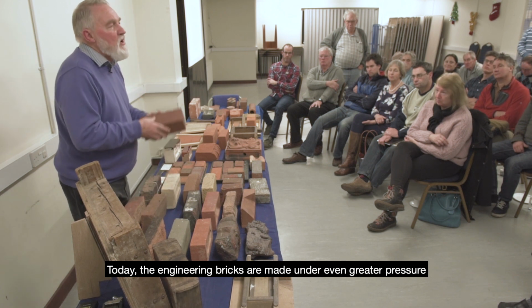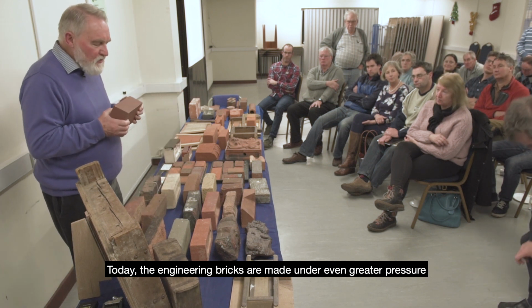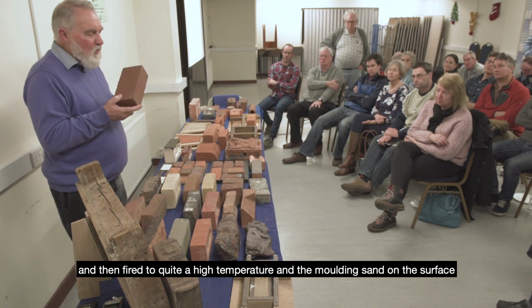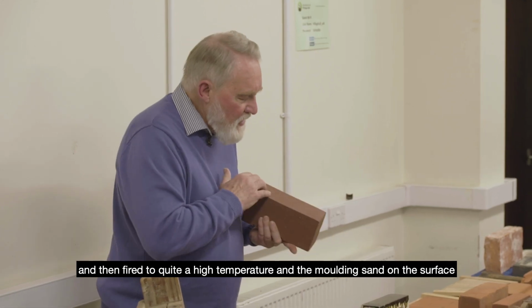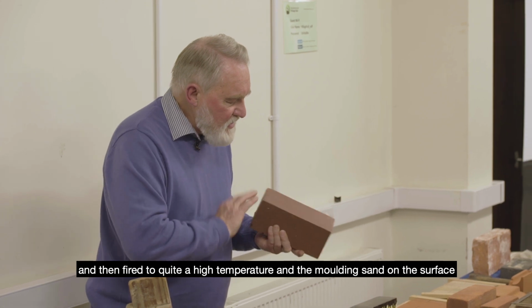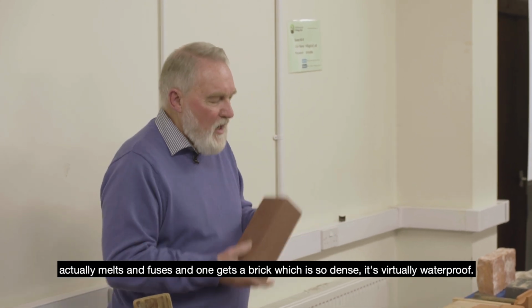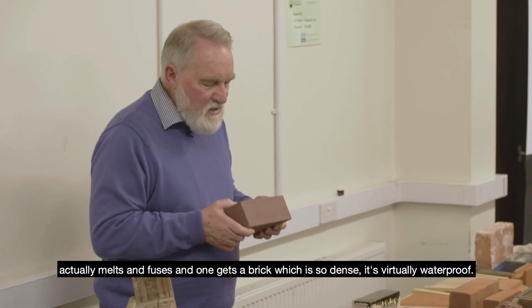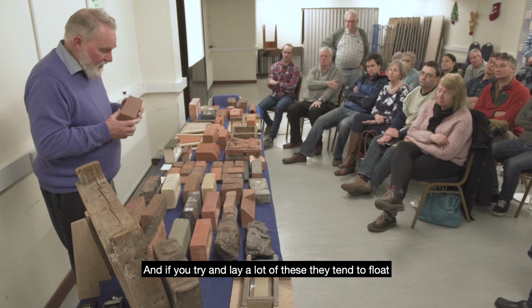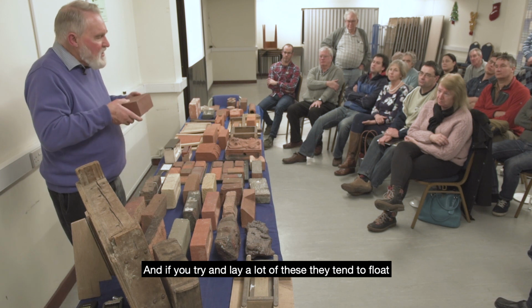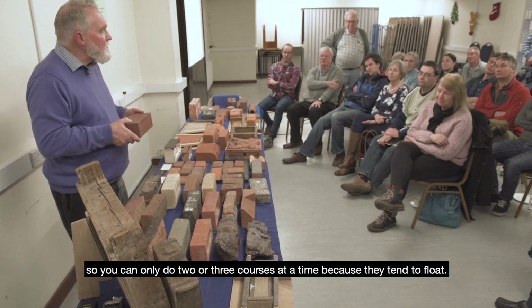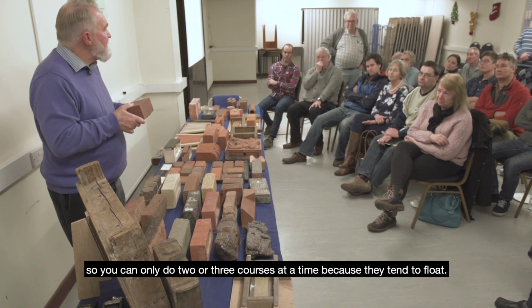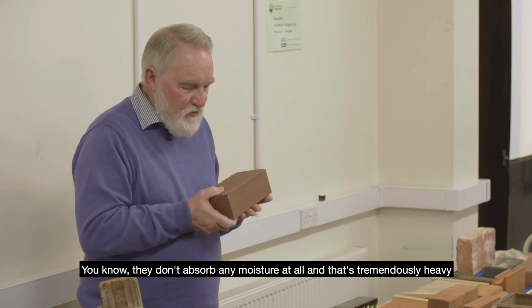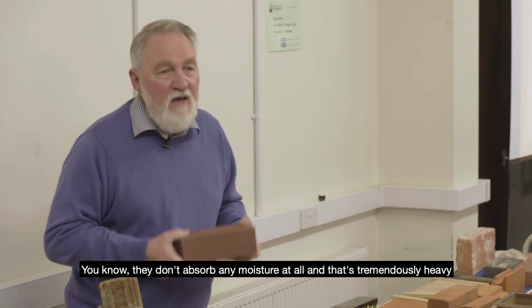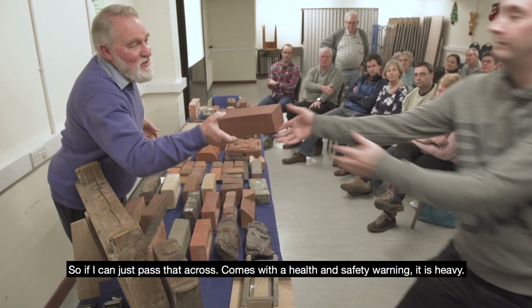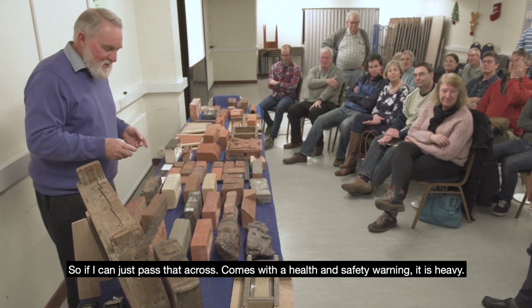Today the engineering bricks are made under even greater pressure and then fired to quite a high temperature, and the moulding sand on the surface actually melts and fuses, and one gets a brick which is so dense it's virtually waterproof. And if you try and lay a lot of these, they tend to float, so you can only do 2 or 3 courses at a time. They don't absorb any moisture at all, and that's tremendously heavy. So if I can just pass that across, it comes with a health and safety warning, it is heavy.